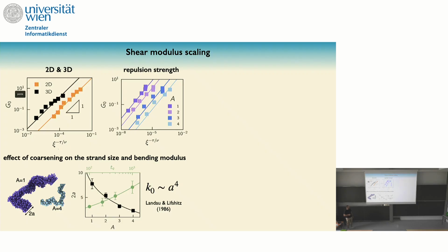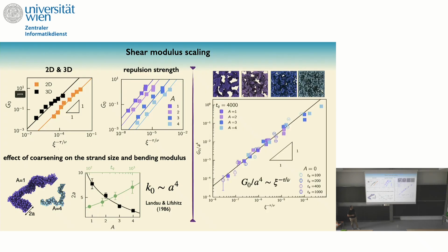And if you go to classical textbooks, you know that the effective bending modulus of a strand depends on the diameter to the power of 4. Then what you can do is take all your data. If this is true, you measure the modulus and you divide by the strand diameter A to the power 4. You plot it as a function of this length scale. And what you find is that no matter what you do to your system, if you change your preparation protocol, your volume fraction, or your interaction potential, they all fall onto a master curve.